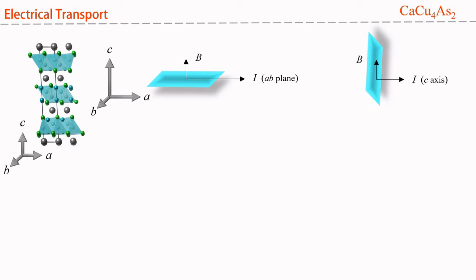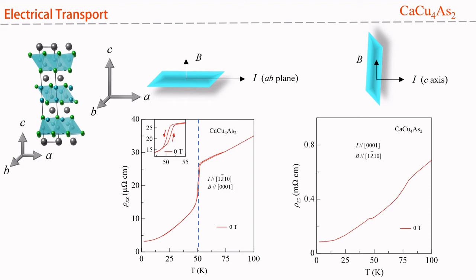A bulk aligned crystal has been used for electrical transport measurement. The electrical current has been passed along crystallographic C direction and AB plane. Here are two such configurations and their temperature dependent resistivity. At zero field, when we apply current along AB plane, the resistivity shows a sharp drop at 51 K and we observe a hysteresis at the transition temperature, while a small anomaly is found for C direction.